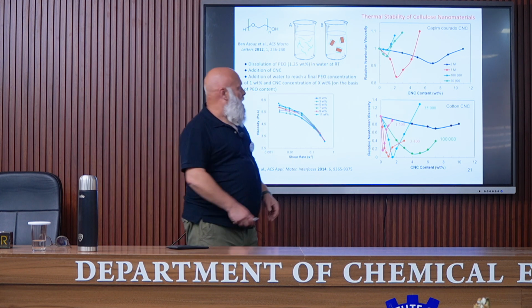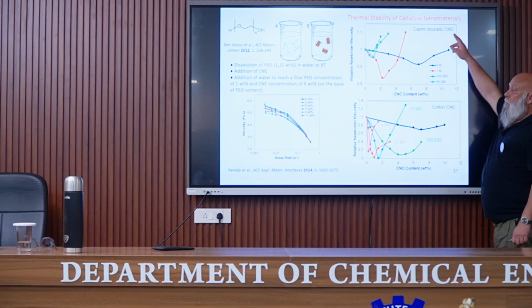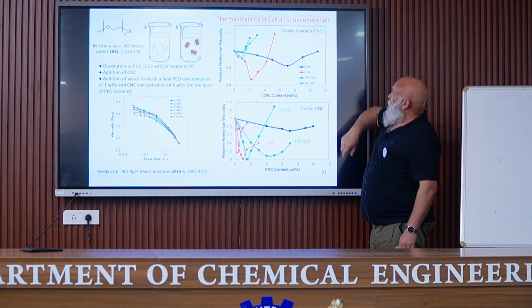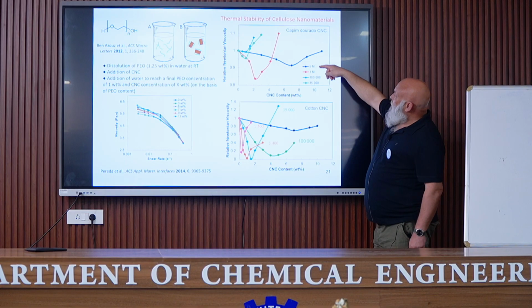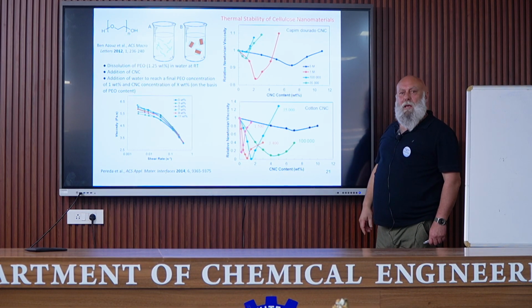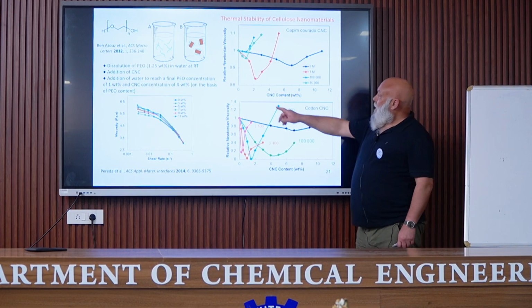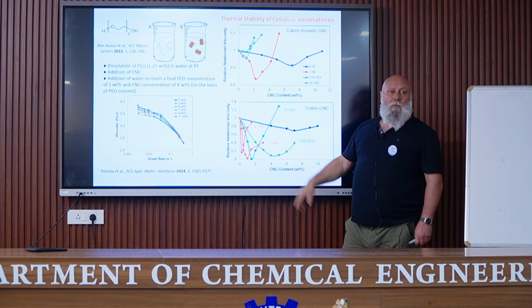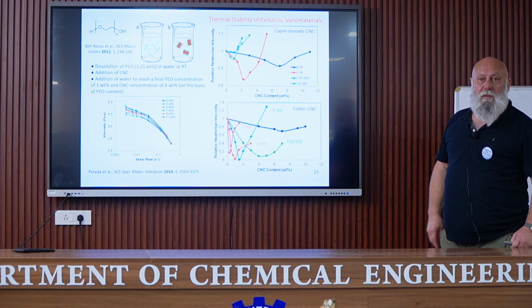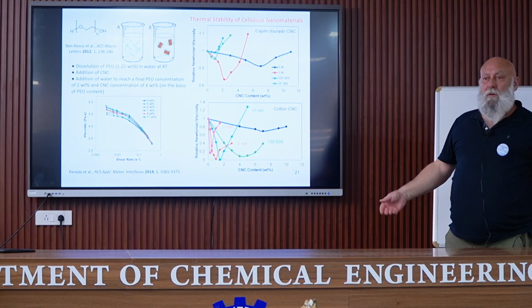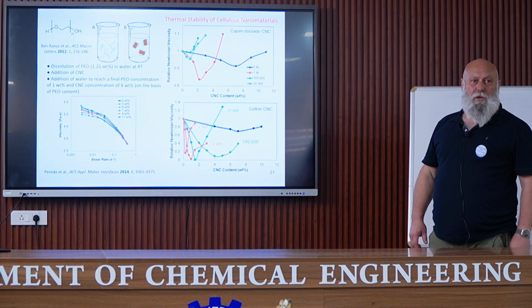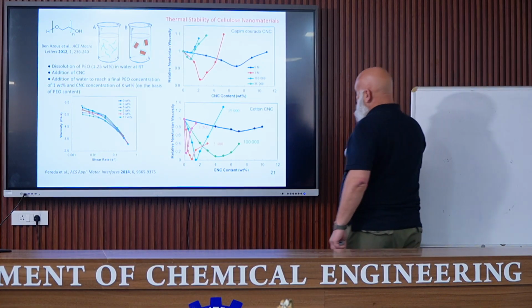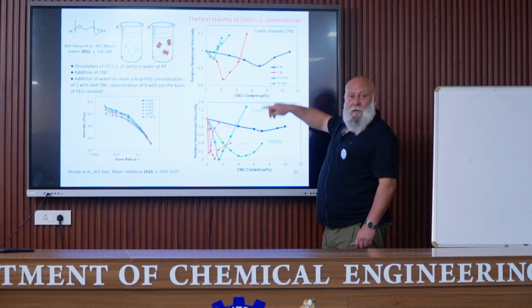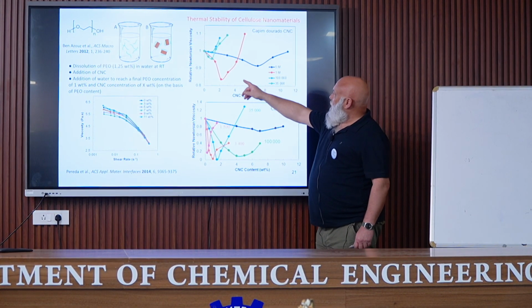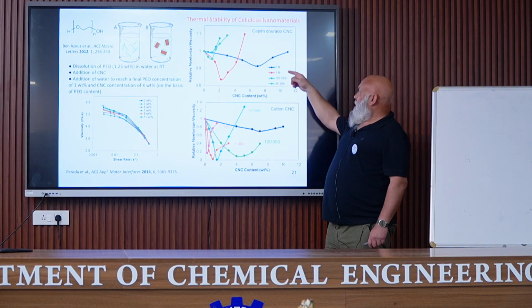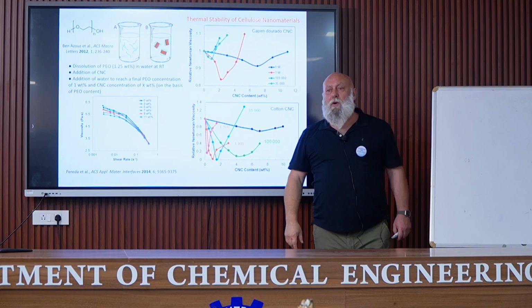So we cannot see too much here, but we can see here. This is for two different kinds of nanocrystals: nanocrystals extracted from Capim dourado or from cotton, with different molecular weights of polyethylene oxide. What you can see is that when adding cellulose nanocrystals, we first observe a decrease in the viscosity, which was not expected. You add nanoparticles to the polymer solution and the viscosity decreases. And then it increases. For both types of nanocrystals, the minimum viscosity decreases when decreasing the molecular weight of polyethylene oxide.